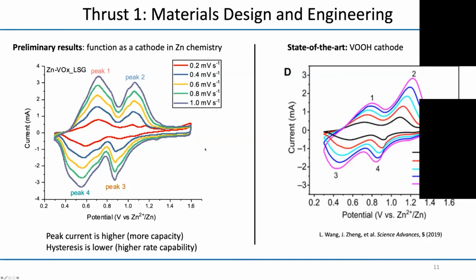And so our proposed future work that we'll pursue in this project is to test the cycling stability to see if we can get thousands of cycles using our cathode material. And if vanadium oxide doesn't work, we also have the option of using manganese precursors to generate manganese oxides that can also serve as our cathode. So that is part of our risk mitigation in thrust 1.